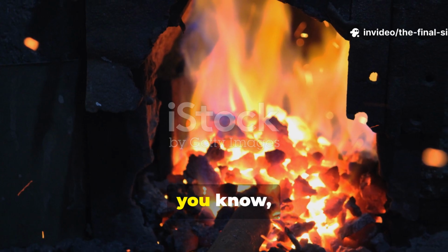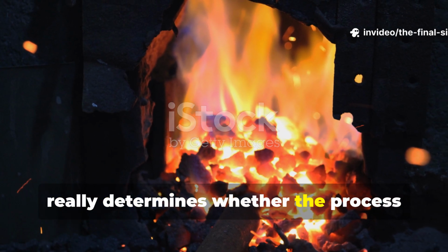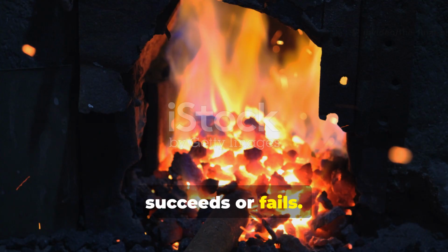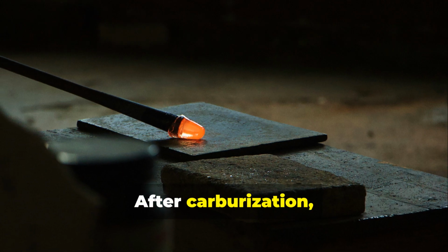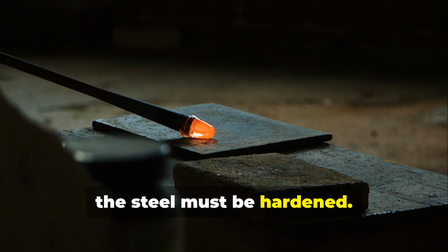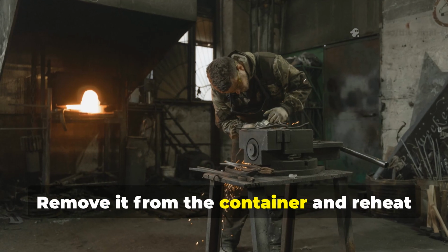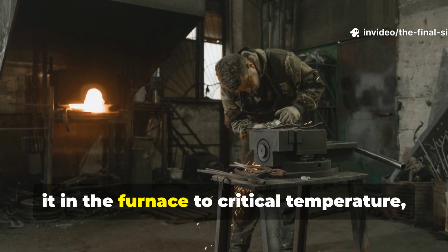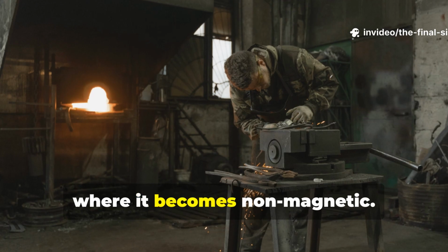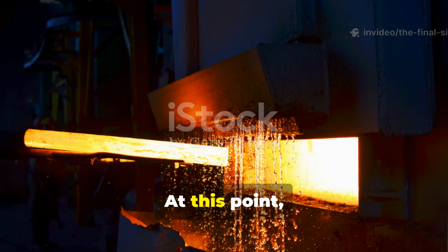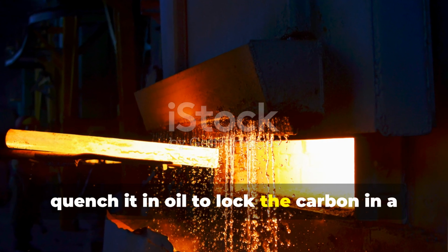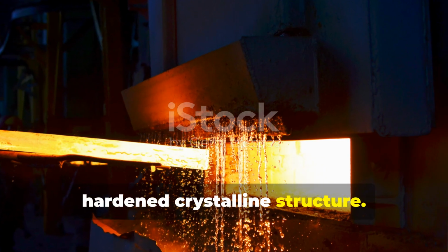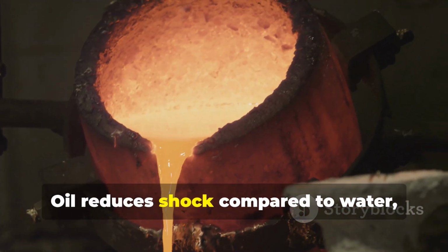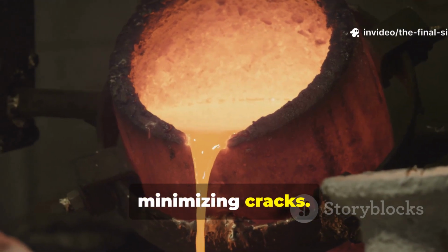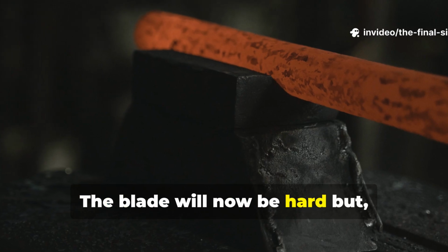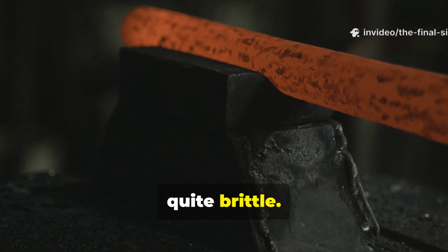Heat treatment really determines whether the process succeeds or fails. After carburization, the steel must be hardened. Remove it from the container and reheat it in the furnace to critical temperature where it becomes non-magnetic. At this point, quench it in oil to lock the carbon in a hardened crystalline structure. Oil reduces shock compared to water, minimizing cracks. The blade will now be hard, but quite brittle.